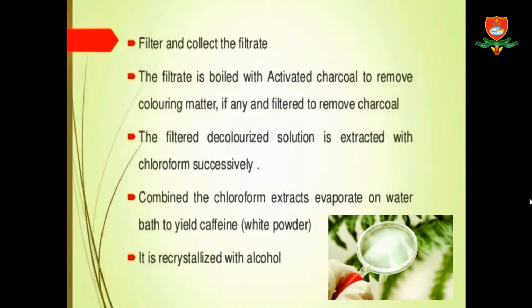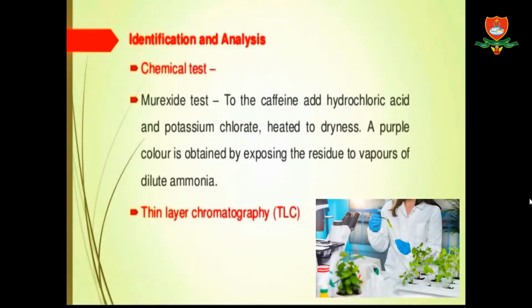The filtrate is collected and boiled with activated charcoal to remove coloring matter, and the charcoal is removed by filtration. The filtered decolorized solution is extracted with chloroform successively. We combine the chloroform extracts and evaporate on a water bath to yield caffeine, which is a white powder. It is recrystallized with alcohol. Next slide, ma'am. We identified and analyzed it with the chemical test called the Murexide test.